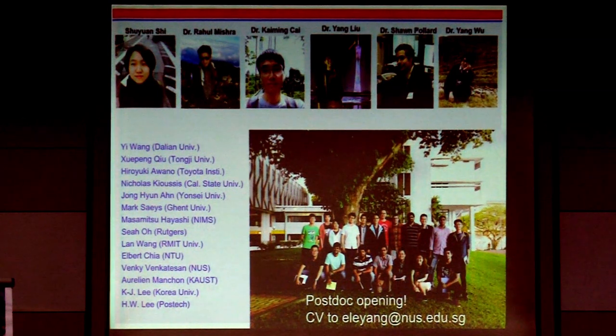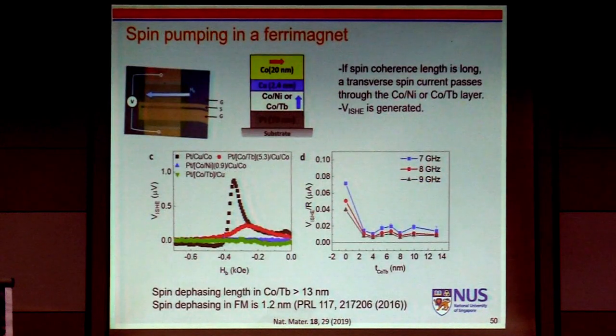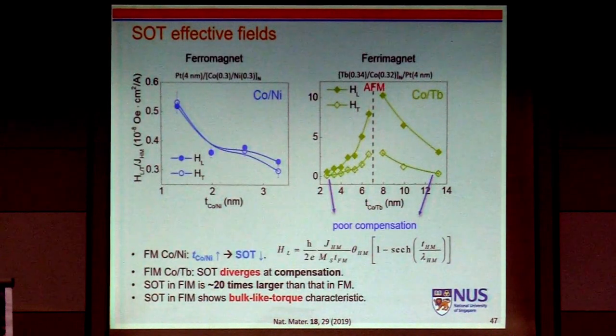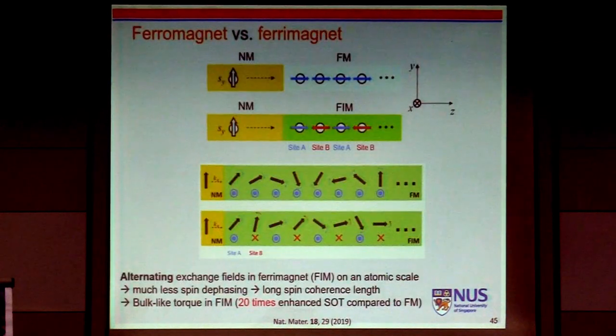In general, can you compare or comment on the difference between ferrimagnets and antiferromagnets in terms of the spin dynamics or movements? Can you briefly comment on the advantage of ferrimagnets compared to antiferromagnets? Well, if you look at a textbook, an antiferromagnet is a special case of a ferrimagnet. For example, in this physics, once you inject spin into a perfect antiferromagnet, the spin diffusion length should be infinite, because you can compensate spin relaxation in an opposite exchange field.